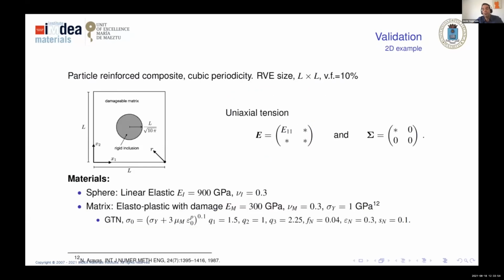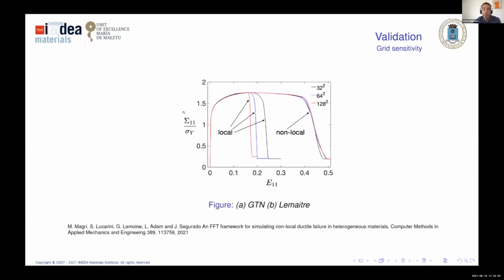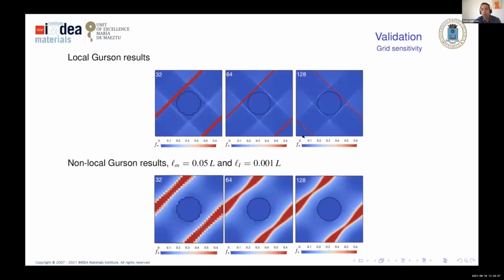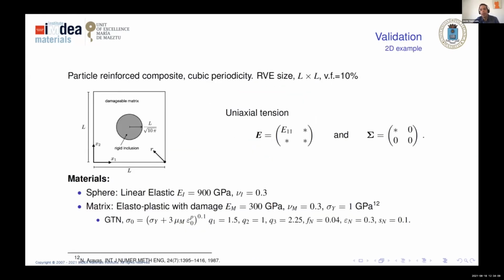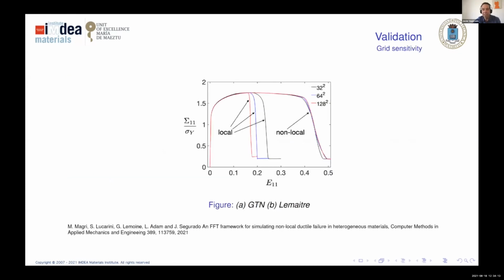Let's first check if we are able to solve the pathological localization problem. We're plotting here the response of local Gurson and here the response of non-local Gurson, where we have three different voxel sizes. The first thing that we see is that the response collapses for the three sizes, so we do not have a pathological size effect anymore. That is the first thing that we want.